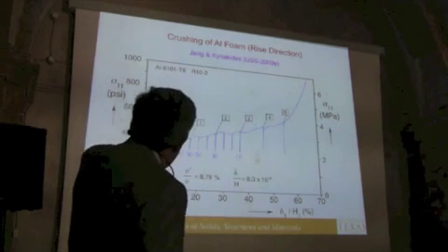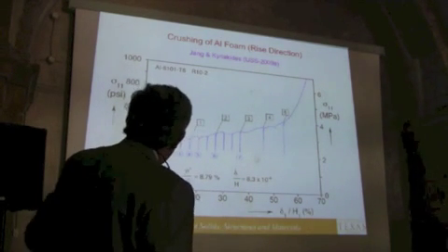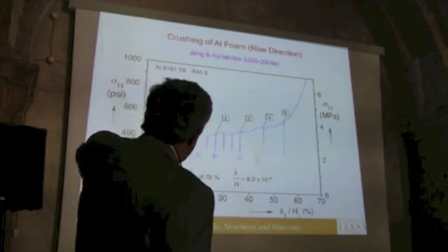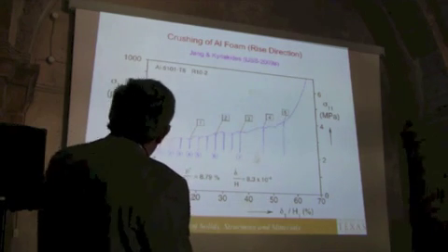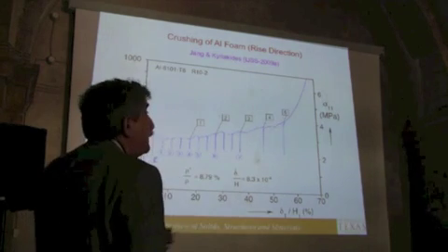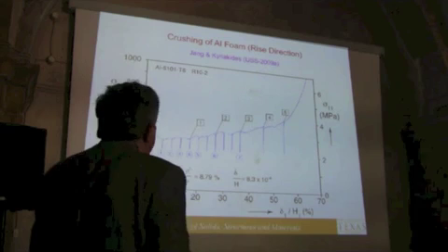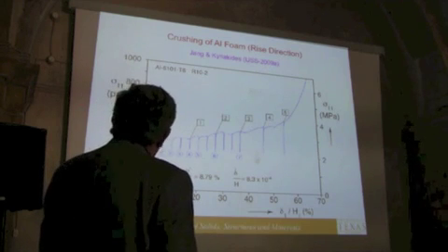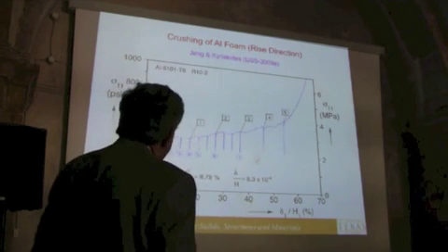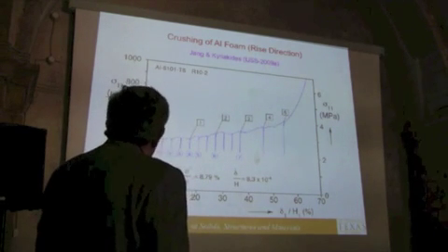It's how does it crash? This is a particular experiment. It's not totally flat because there is some variation in relative density through the specimen. The specimen is about 100 millimeters tall and about 50 by 50 millimeters square. Strain, this is the shortening divided by the original height. Okay, but what was special about this?